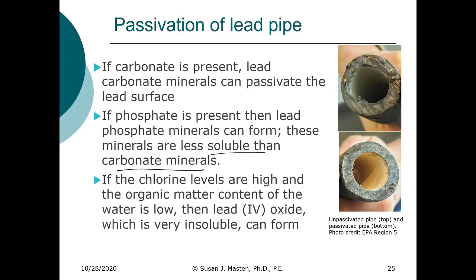If the chlorine levels are high and the organic matter is low, you can form lead 4 oxides, and these are extremely insoluble. So what you see here is a passivated pipe. This has some, looks like a white coating in here. It's actually irregular. And this is likely to be either a lead hydroxide or a lead carbonate. We don't know based on the photo. But it doesn't completely cover and coat the inside.